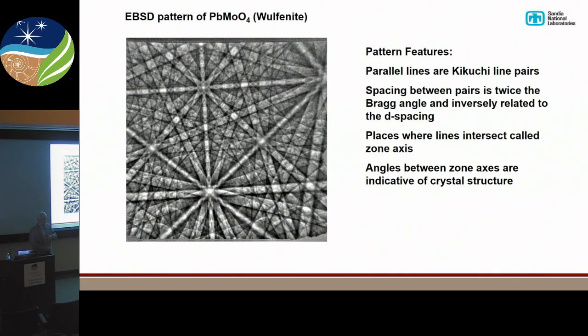And that's the other nice thing, and thank you for bringing that up because I forgot to say, when you look at TEM, you look at an angular space that's maybe 6 degrees, maybe 7 degrees on a new TEM. Here we're seeing nearly 90 degrees of diffraction space in one shot. So it's really nice for actually doing crystal structures. There's other features in here that we can use. I don't know if you see these parabolic or circular features. Those are actually the intersection of the Ewald sphere with high order Laue zones. And that also gives us a spacing coming out of the page in the crystal structure. So we can do some other sort of reduced cell calculations. Anybody who does X-ray here, you can do reduced cell calculations to actually identify the phase from one pattern, or at least identify the crystal structure.